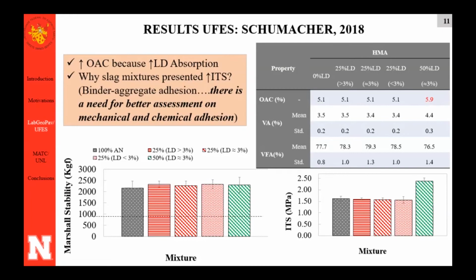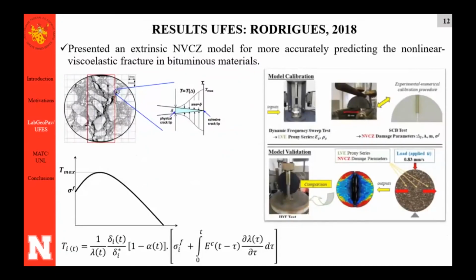This result caught our attention, and we thought, wow, if I replace natural aggregate by slag in higher amounts, I increase the indirect tensile strength. Why did that happen? Better adhesion? There are some papers trying to investigate adhesion between slag and asphalt binder. Or because I use more binder, it could also be that reason. So there is a need for a better assessment of mechanical and chemical adhesion. And I leave this question now because it will be answered with the results that I got from UNL, with the UNL collaboration.